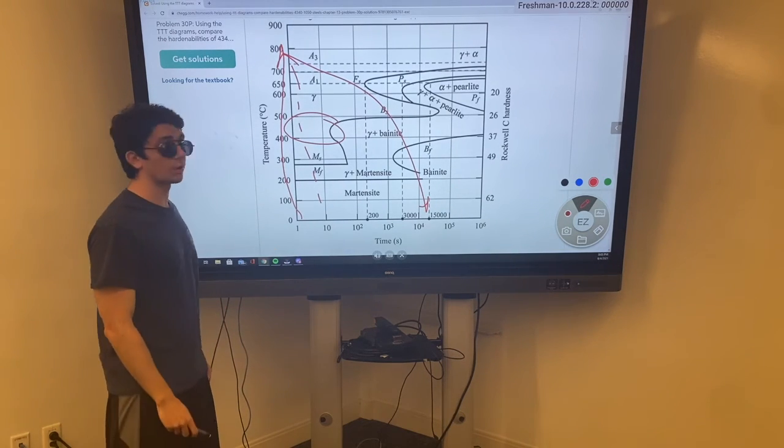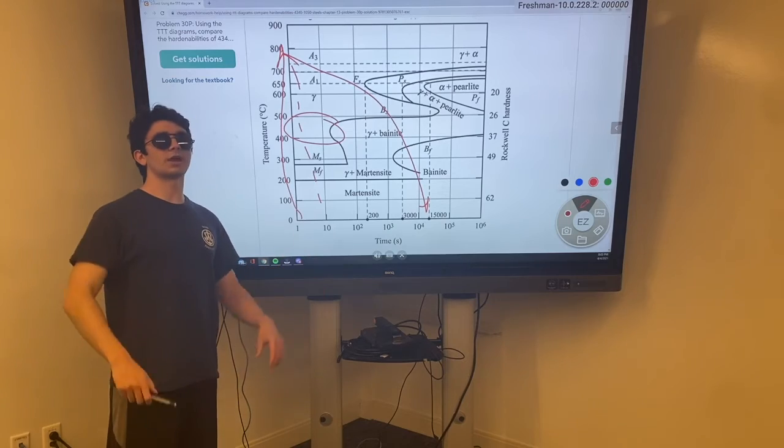So, how do we slow the cooling rate? Well, you can preheat the weldment or you can cover it afterwards.